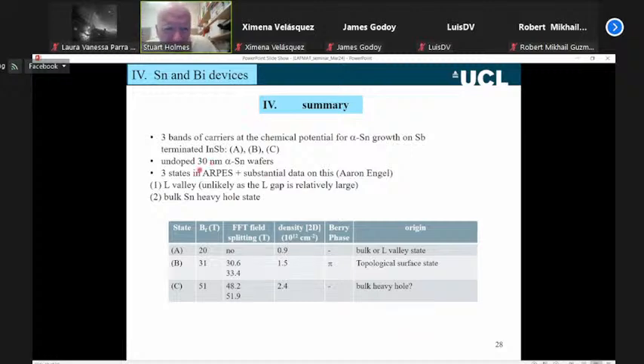As I say, they're 30 nanometer films, thin films of alpha tin. We've identified these 3 states. Now, it could be that one of the states that we're seeing is a so-called L minimum. That's a secondary minimum in the conduction band that's accidentally close to the chemical potential. We could have a bulk heavy hole state possibly coming in. But we've also got this topological surface state. We know we've got this topological surface state because it has this Berry phase of pi from the magnetoresistance.